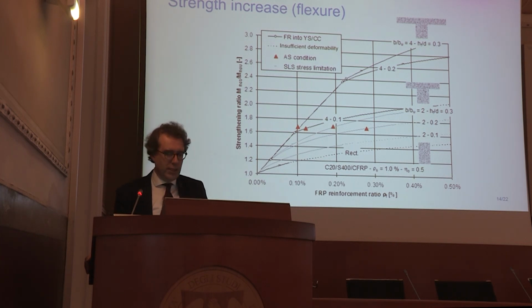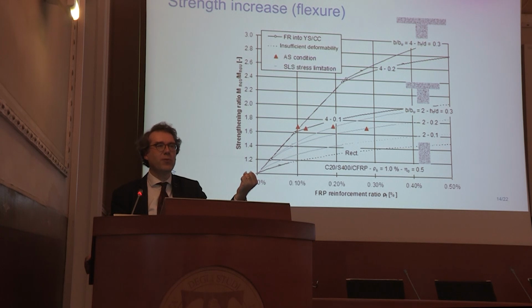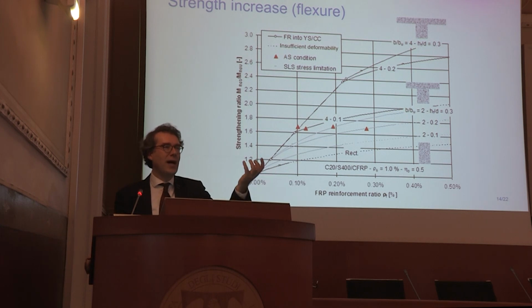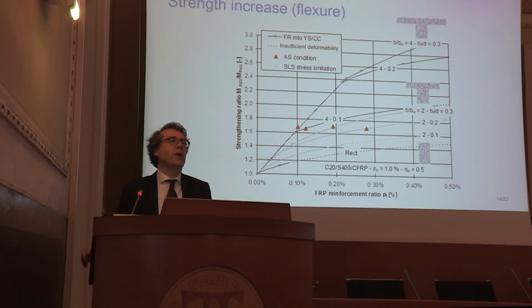For example, the lower curves refer to strengthening of a rectangular beam. The compression zone is limited in such a beam, and as we're providing the FRP reinforcement as extra tensile reinforcement, which needs to match up with your compression zone at the top of your beam, given the equilibrium between both, that means the more tensile capacity you add, the more you demand from your existing concrete, which will act in compression.